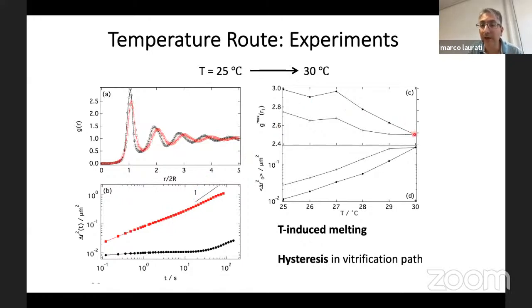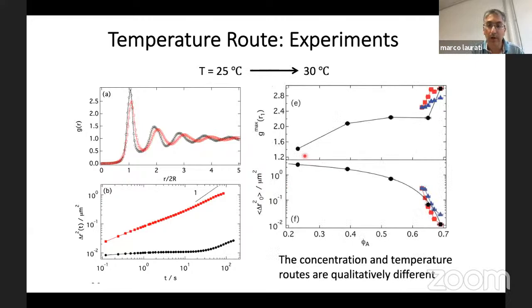And then from this state, we decreased the temperature again down to 25 degrees. And as you can see, both in the structure and in the dynamics, we could observe a hysteresis. So essentially, doing steps of finite time at each temperature, we don't go back along the same route, but the system goes back along a different route, with a less structured system which shows faster dynamics. And even if you compare the routes at equivalent packing fractions, through the concentration route or through the variation of the temperature, you see that they follow different paths.